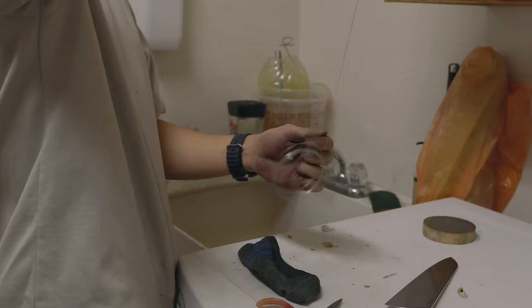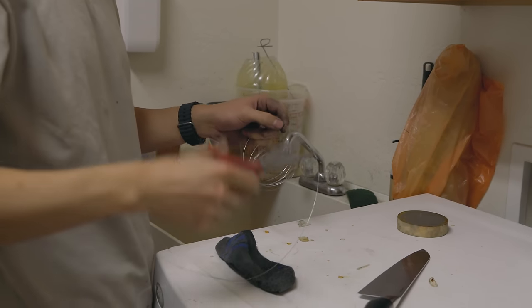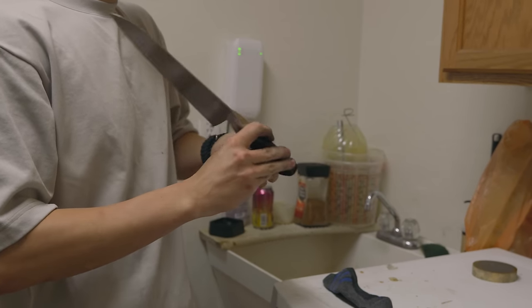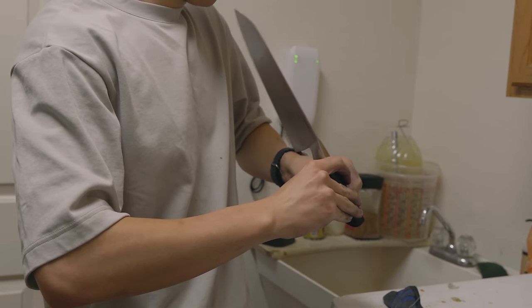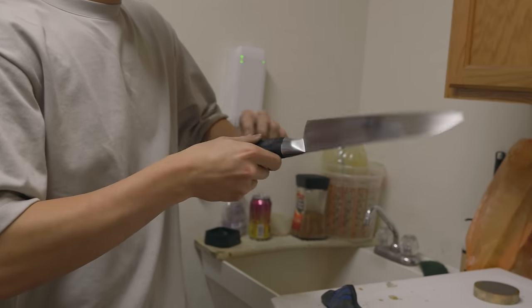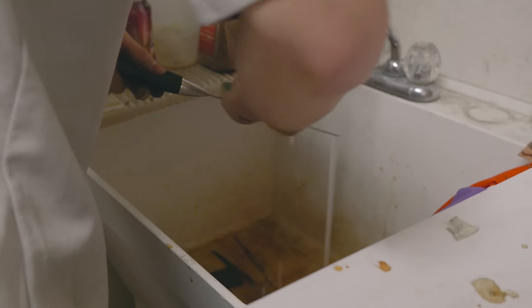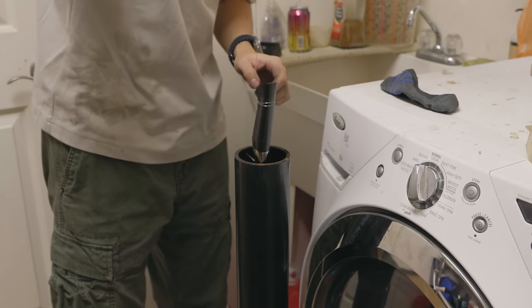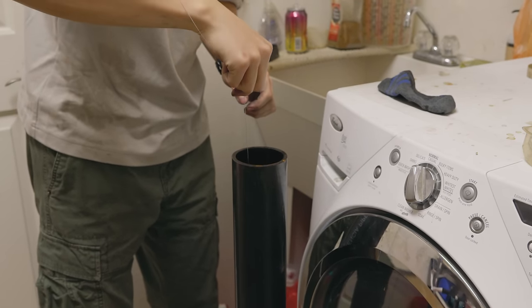With my maker's mark now etched and darkened, it was time to start thinking about etching the actual blade itself. I'm just using the wire here as a method of dipping the blade in and out of the ferric because my tank is like four feet tall. The thing that I use to clean my blade before I etch is actually just regular dish soap. I've tried to use degreasers and acetone, but they always leave like little splotches. Dish soap has left a pristine finish every single time that I've ever used it.